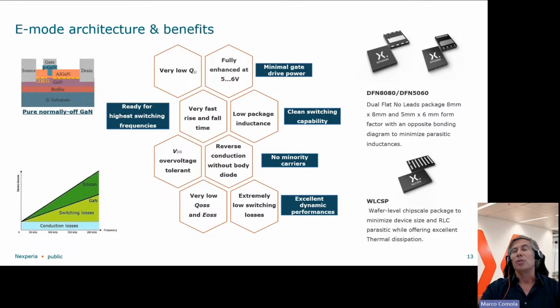And so lower switching losses, higher efficiency. And you can drive an E-Mode normally because the VTH is 1.5 typical value. You can drive at 5-6 volt, so you have a minimal gate drive power. We put the GaN die in a package that is a low inductance package. It could be, for instance, a DFN 88 or DFN 5060, so 5 millimeter by 6 millimeter, or 8 millimeter by 8 millimeter.